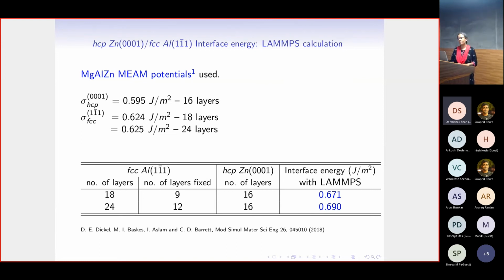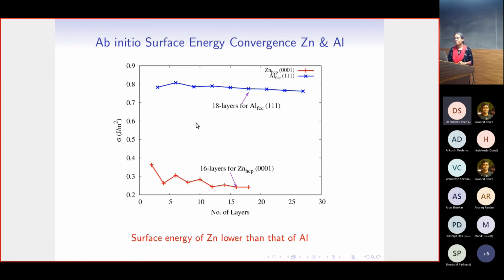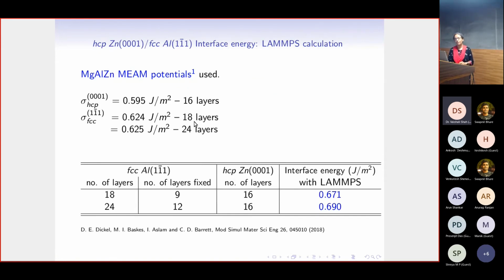So we use this potential and obtain the surface energies for the HCP and the FCC surfaces. As you can see here, this FCC is fairly well converged, but it doesn't have as good a convergence profile as the zinc HCP phase. We did the surface energy calculations for two surface thicknesses: an 18-layer thick surface and a 24-layer thick surface.